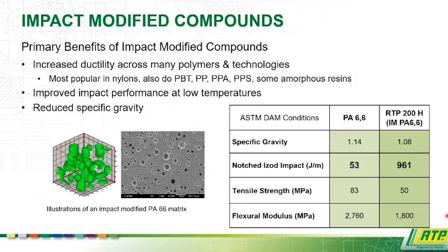So if we look at a common material that's impact modified, like I mentioned, nylon 6,6. That's probably the most ubiquitous out there. If we look at what that looks like in impact modified version under our RTP 200H, your notched IZOD impact goes from only around 53 joules per meter to 961. So a dramatic, almost 20-fold increase in your impact resistance.